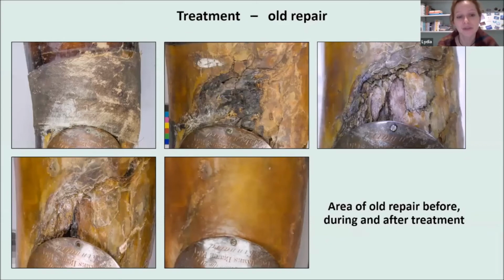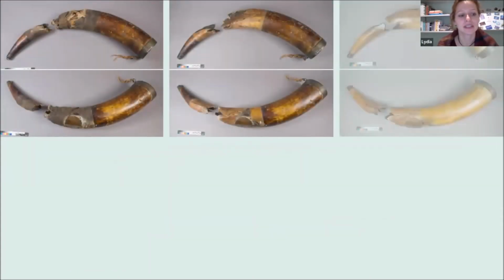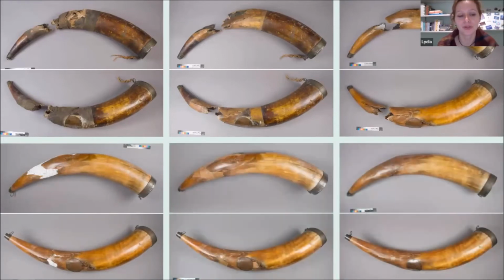Zooming into the area of the old fill, which was hidden underneath the bandages, I would like to show you how this area transformed during treatment from hidden, deformed, and unstable horn material and fills to a stable area with a discreet fill. And here is the entire horn in its different stages before, during, and after conservation. The treatment of the horn took me in total 260 hours, which is about 8 weeks or 2 months. And that's only counting the actual treatment time, but not the time when I humidified it in between.